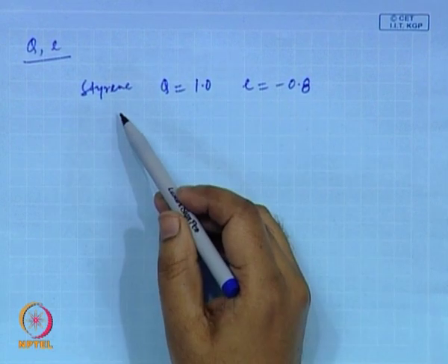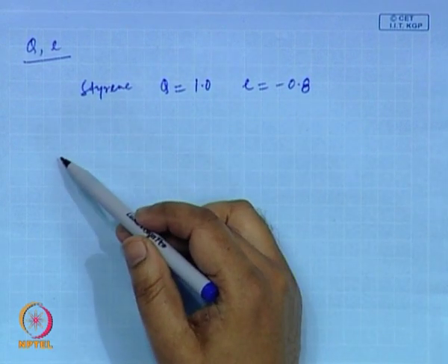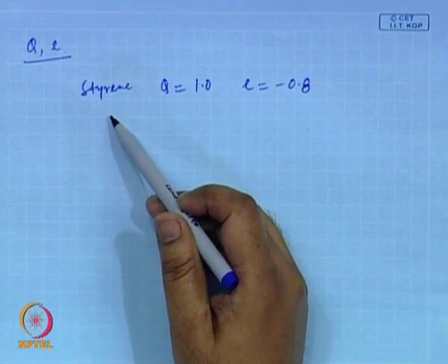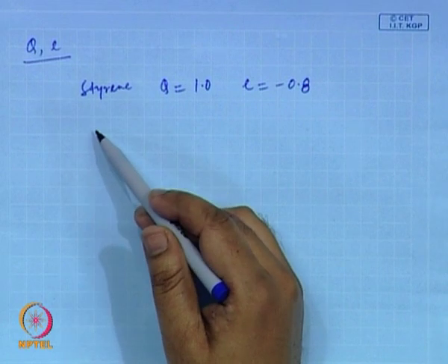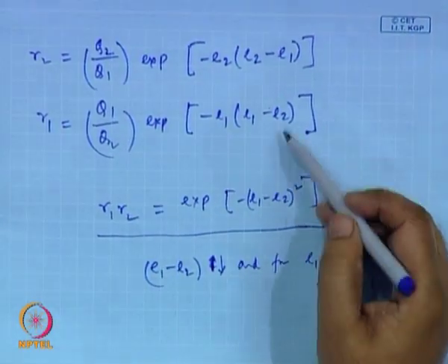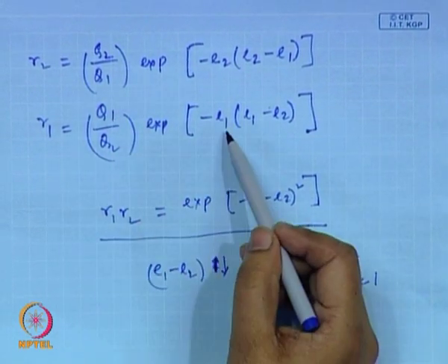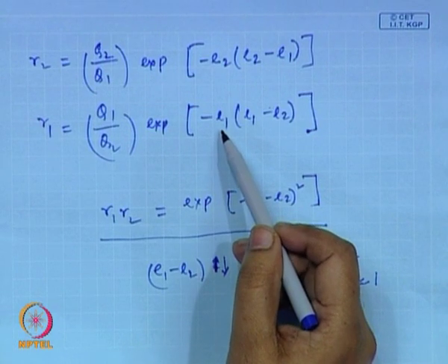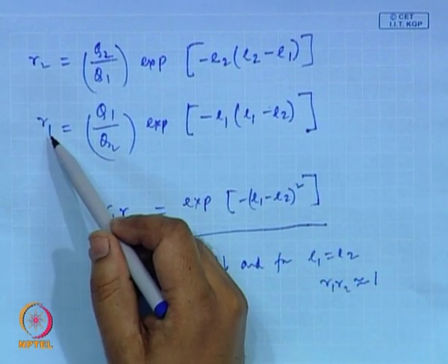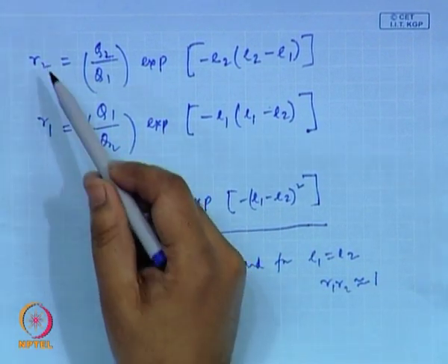What happens? Individual monomers are copolymerized with styrene, and from the experimental values of R1 and R2, you can use these expressions. If you consider 1 as styrene, then you know Q1 and E1, and you also know R1 and R1R2 from experiment.